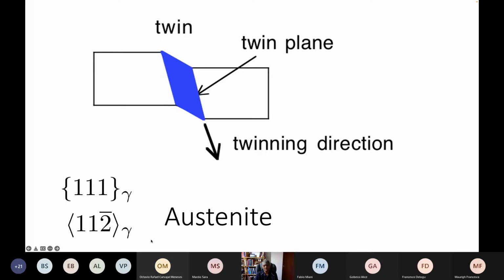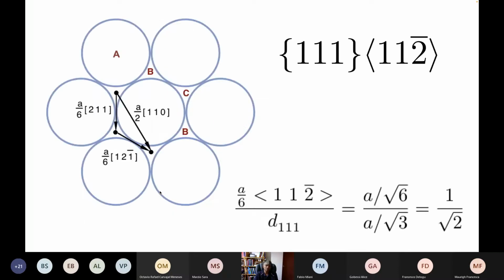Okay, so I'll repeat that. The twinning system in austenite consists of a twin plane, which is the close-packed plane of the austenite, and a twinning direction within that plane, which is of the type 112. I will illustrate that later, but that is the twinning direction, which is the 11-bar-2 in this case, and the twin plane is the plane which remains unaffected by the twinning deformation, which is the 111 plane of the austenite. And of course, we know that the 111 plane is close-packed, which means that the atoms touch along all three directions, and there's a high packing density inside that plane.